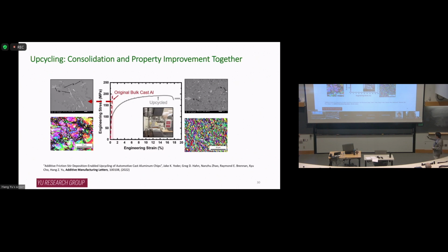The red is the original bulk-scale cast aluminum alloy. It's brittle because you put a lot of silicon there to improve the castability. The large silicon particles kill the ductility. But after deposition, our material becomes more ductile. Essentially, you see significant strain hardening. So why is that? If you examine the microstructure and compare the feedstock material, which is machine chips, versus the deposit material, you'll see the secret. Of course, we have a grain structure change because of dynamic recrystallization.